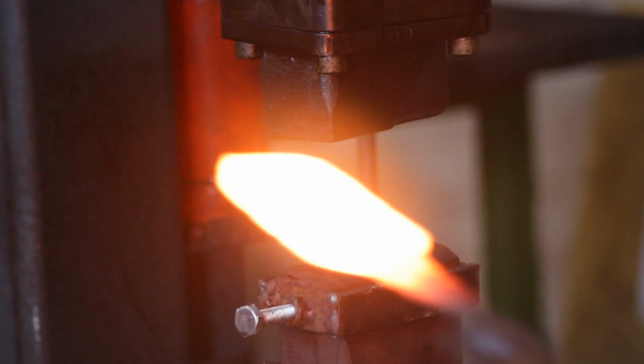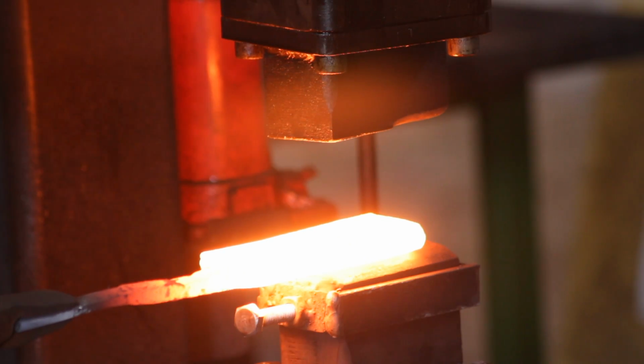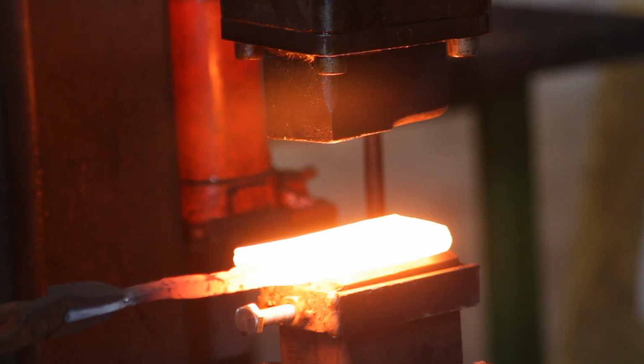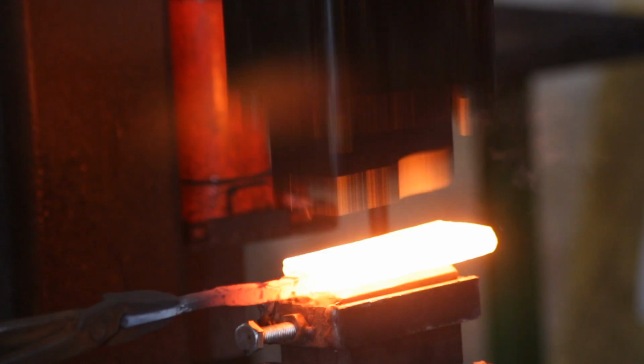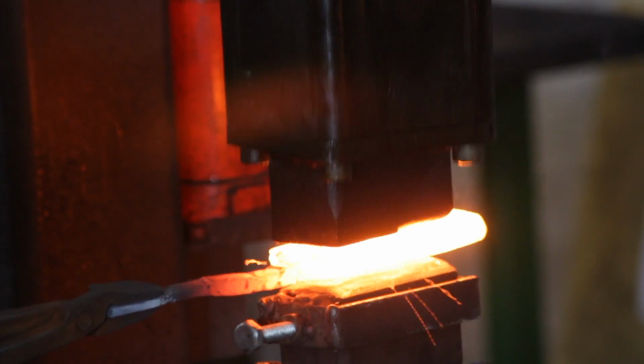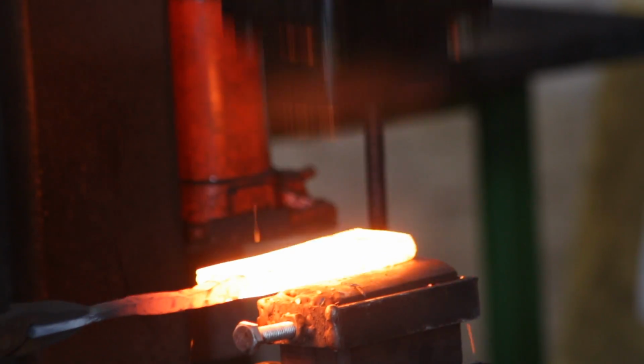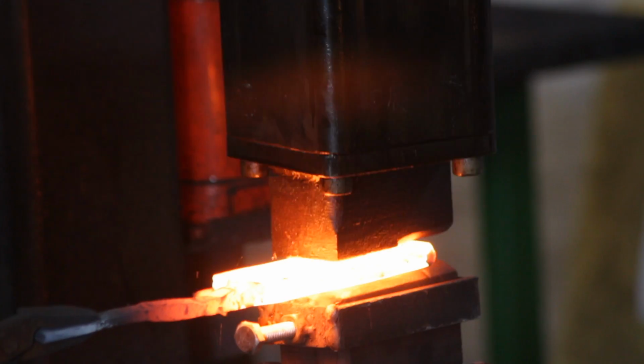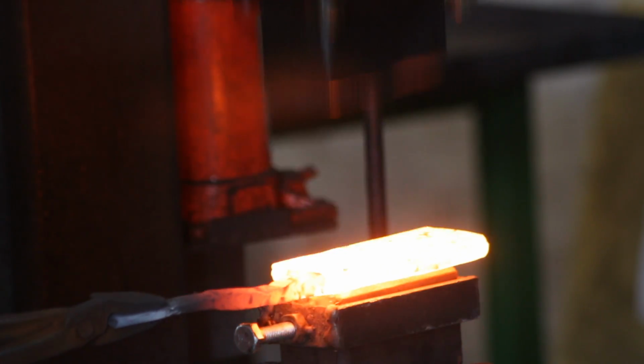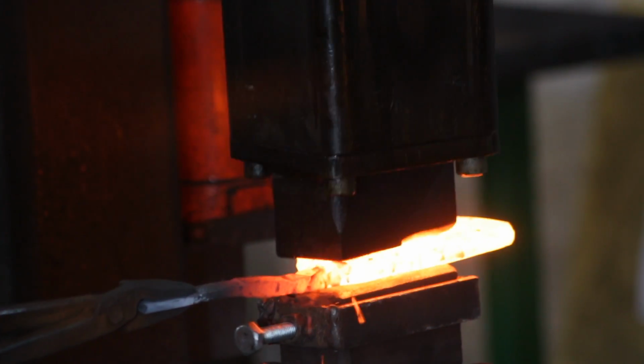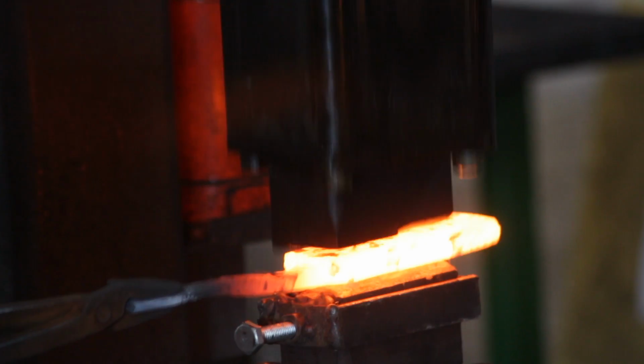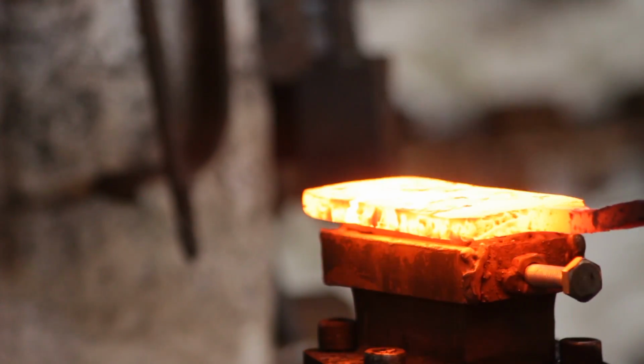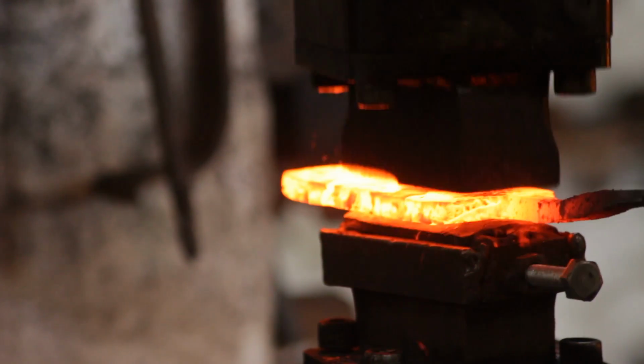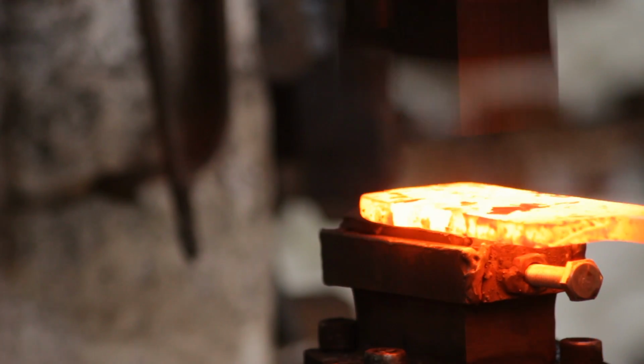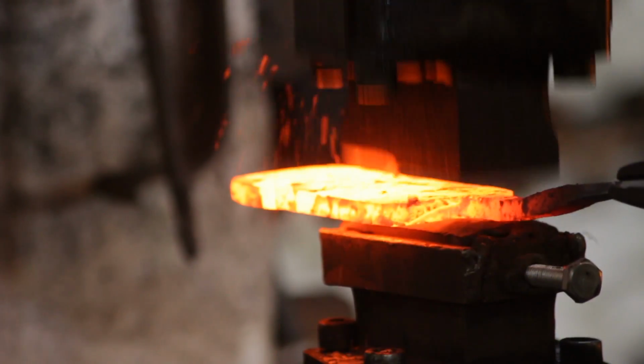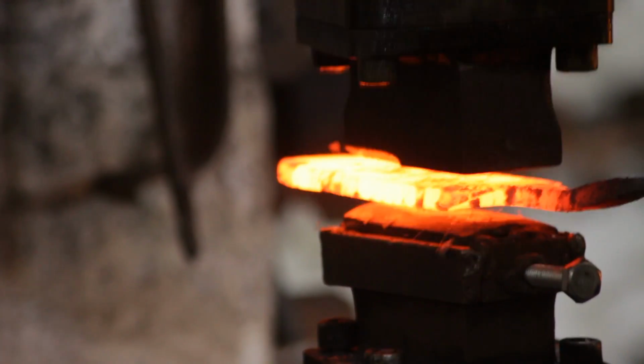So then I put my drawing die on the power hammer. This is just a piece of handrail with a welded frame around it. And I will spread that material out. So I spread it out to about 65mm, which is more than it needs to be, because we want a 19mm internal diameter socket. So ideally you want about 60mm.